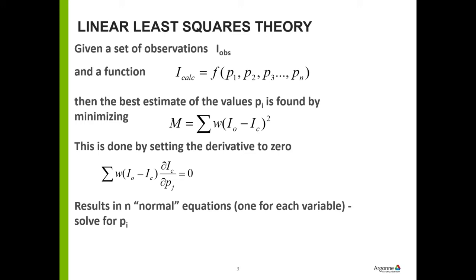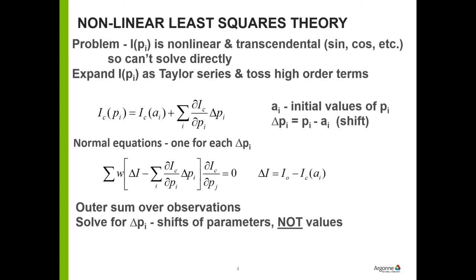That's fine if it's a linear problem. The problem with powder diffraction patterns and single crystal crystallography and all sorts of things like that is the functions are not linear. They're not even polynomials. They're much more complicated than that because they have transcendentals in them, namely things that do this. So you can't solve these things directly starting from nothing.